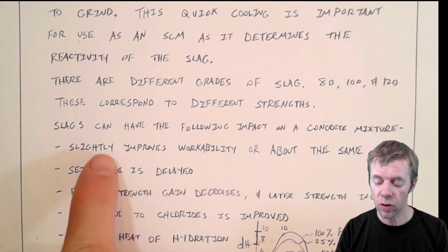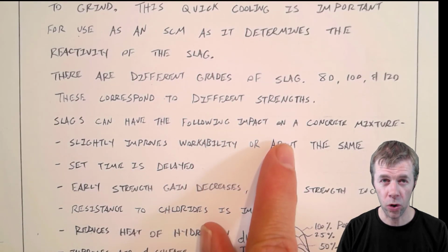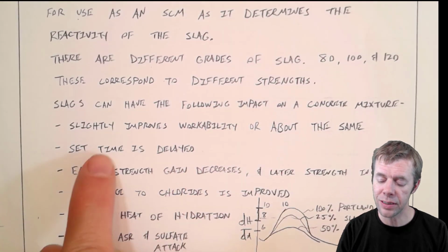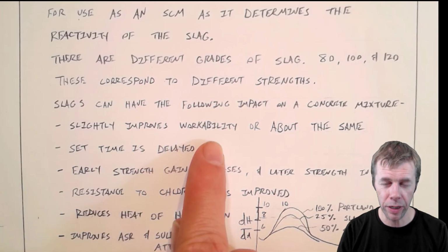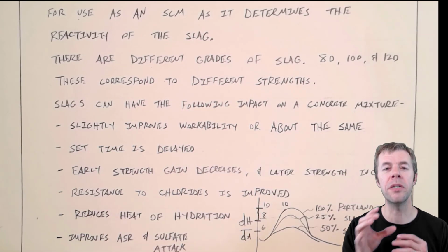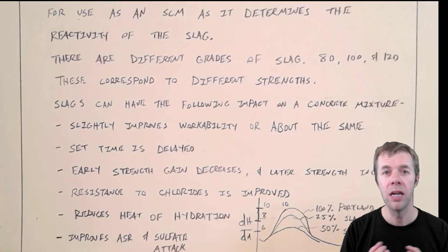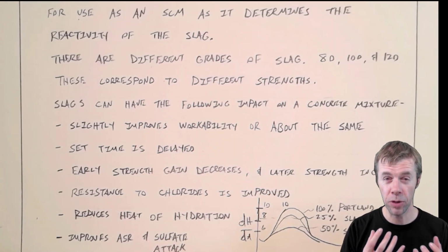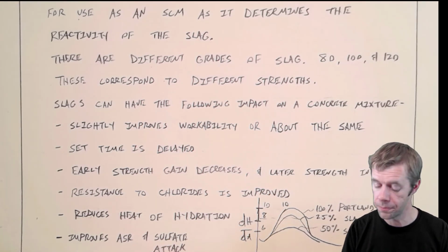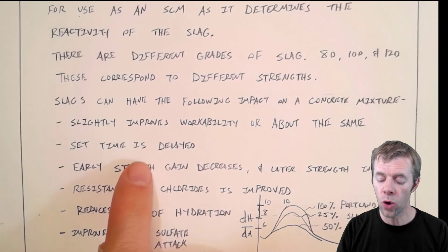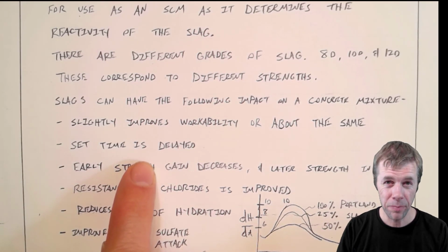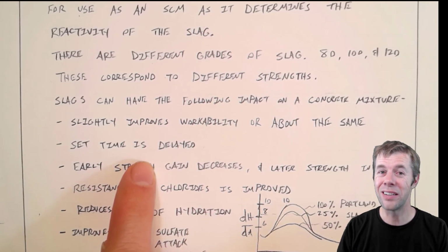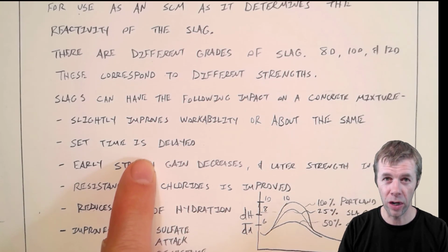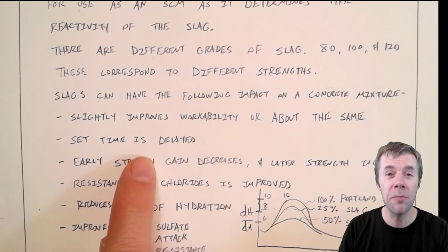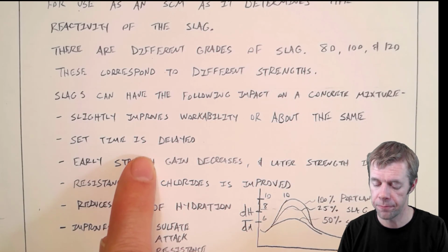So slags can have a lot of different impacts on actual concrete mixtures, and they can slightly improve the workability or make it about the same. They're a slightly different shape than Portland cement, so that can help some things sometimes, but sometimes you don't see any difference at all. But you almost always delay your set time because it's not as reactive early on as Portland cement. And that can be a good thing. It can be a very good thing.